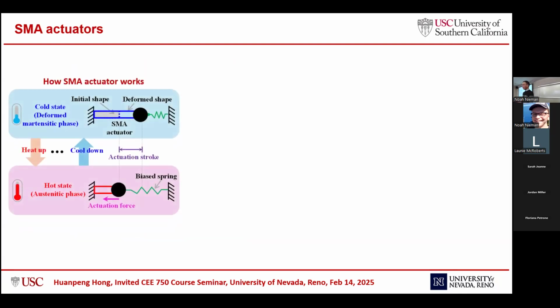So here's the schematic of how the shape memory alloy actuator works. If it starts from the cold temperature and the initial length, and we give it some kind of biased force, it can be either gravity or a biased spring, it will have some deformation into a deformed shape. It is in a cold state. And if we heat this material up into a hot state, the phase transformation will occur, and this material will shrink and generate an actuation force. This shrink, the distance change, is called the actuation stroke. And the magic thing is that this material can not only shrink by itself, if we cool it down, it can expand again. So this is a reversible and repeatable process. That's why it can be used to make an actuator.